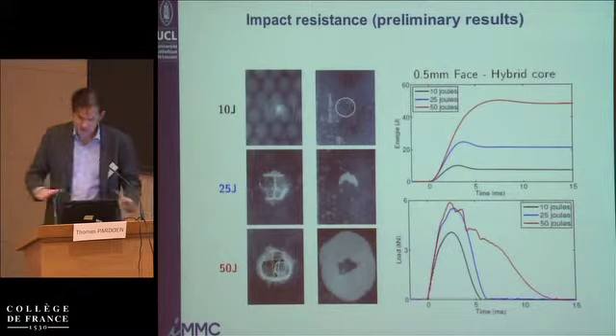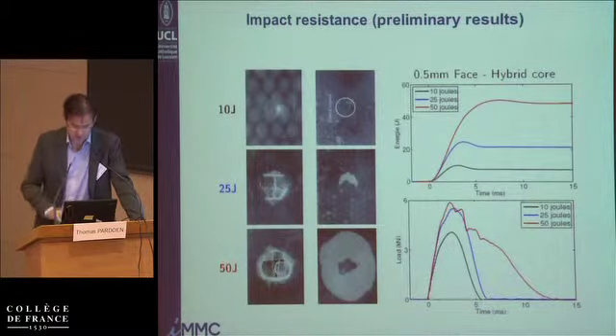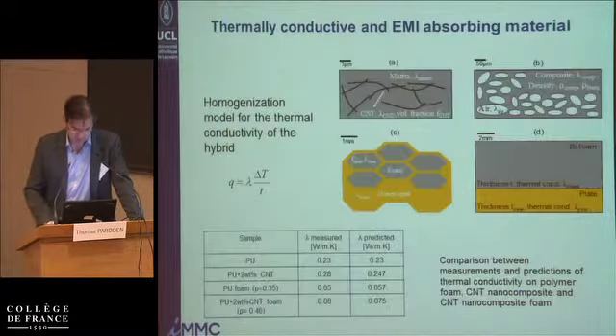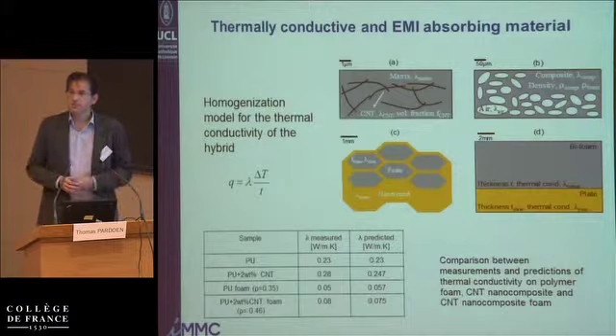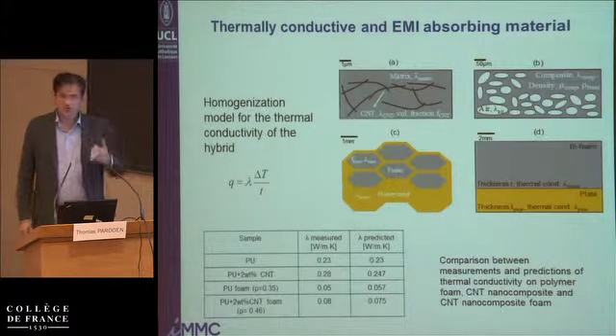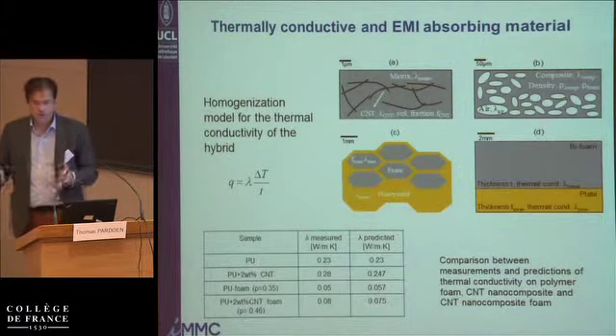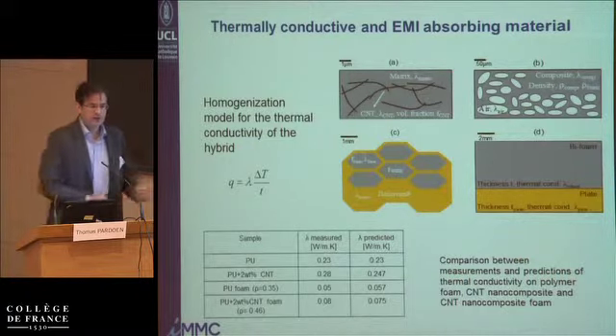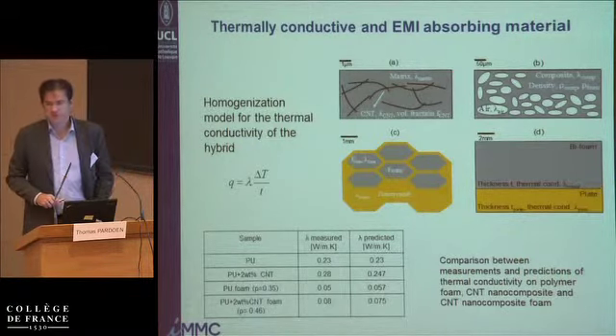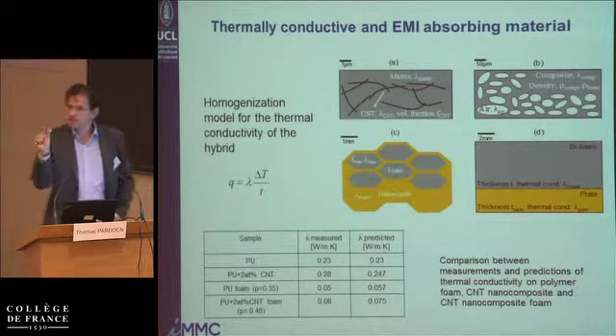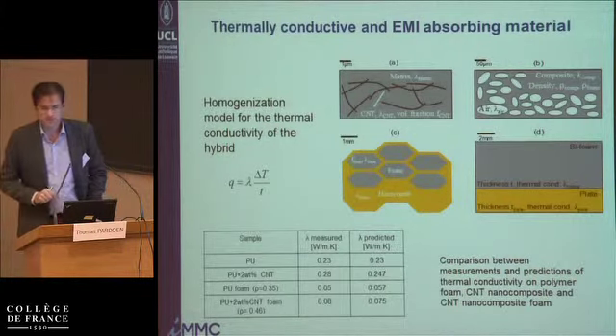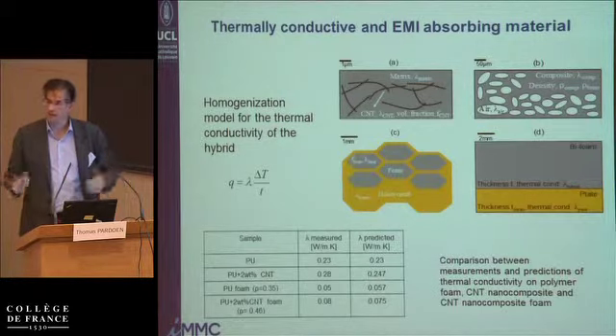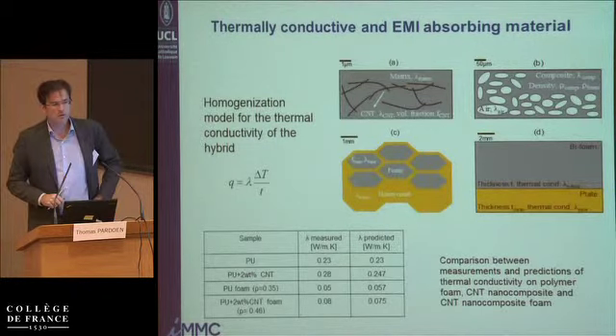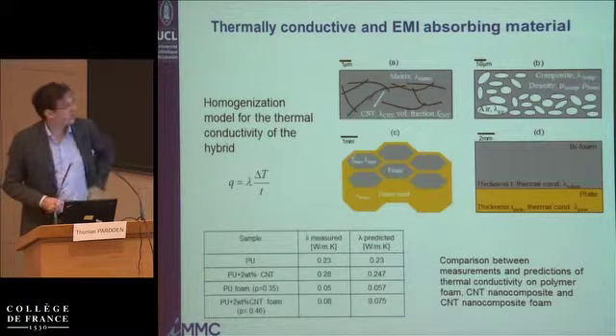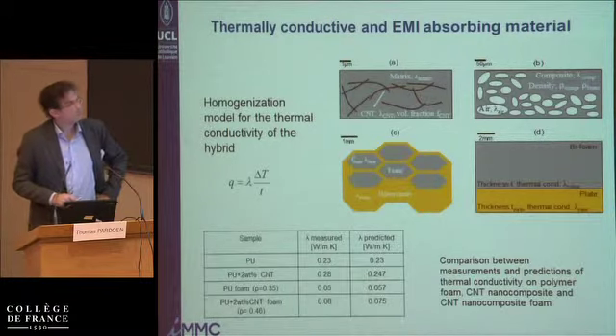It's better also, and for the range of parameters we have tested, we avoid complete penetration owing to the presence of the foam. This is for mechanical properties, and there are some reports in the literature explaining how to optimize a foam-filled honeycomb, and perhaps you will not save mass, but you might save in terms of the thickness at the end.